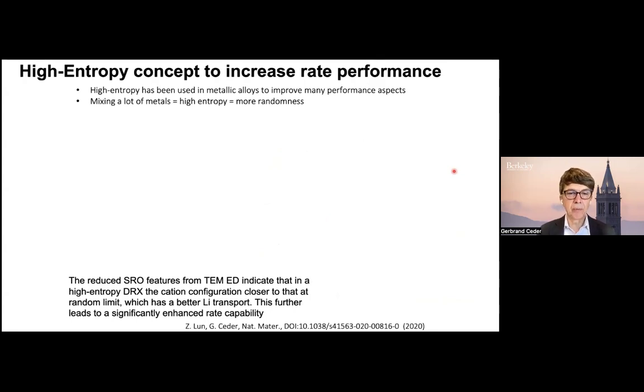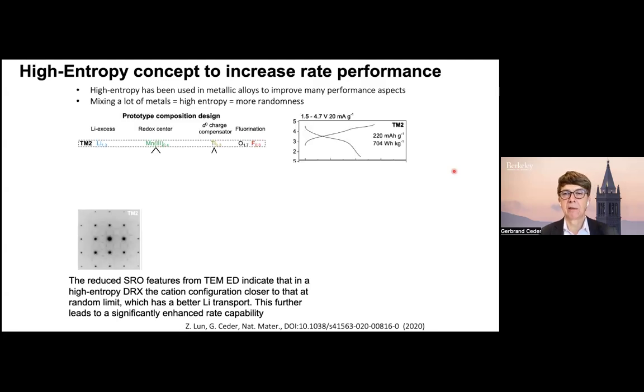One is sort of a cute one, maybe less practical, but it's been known in the field of metals that you can use the high entropy concept to decrease short-range order. So we read about that actually from one of my colleagues here in Berkeley. And then I said, oh, let's try this in DRX cathodes. So we did a systematic experiment where we mixed more and more metals in the DRX. And so I'm going to show you something with 2 transition metals, 4, and then 6. And then we also even did 12 just for the sport.